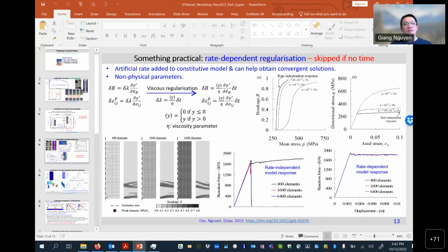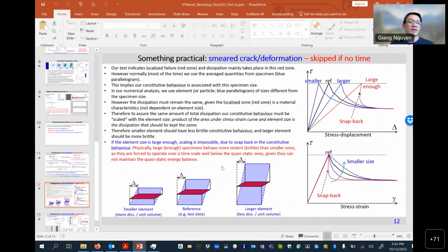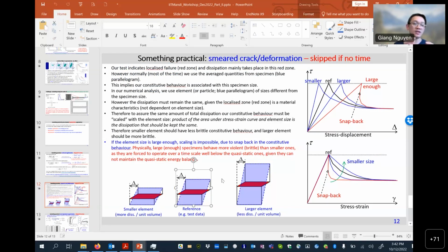Yes. So this is the practical approach. Say we are not able to work out the true behavior inside the band, right? We can use the macro behavior, but we need to keep track of the size of the specimen. If we run the test with that size, our constitutive relationship, after being calibrated with the data we get from that specimen, is associated with that size. So it should go with that size. And in finite element, if you use a larger size, then you have to scale the constitutive behavior with the size.